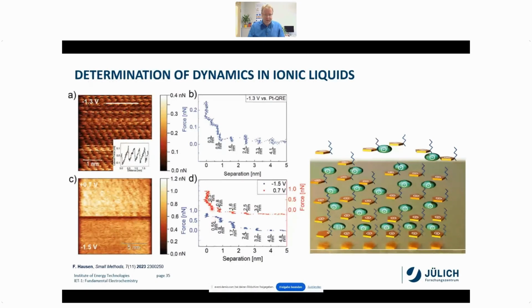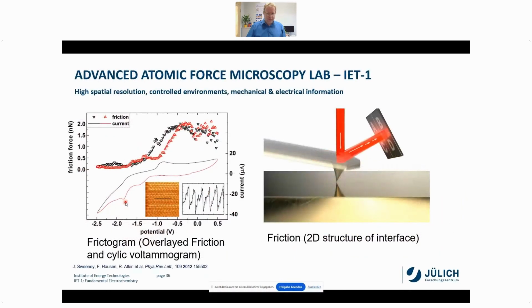And now you might wonder, if we have a positive potential, why this is the cation. That is just because we're scanning here not at the substrate, but we're scanning at these anion layer. So the first layer which you penetrate through is the cation, and at negative potentials, vice versa. So we can see here that we are not at the gold film. So if we now look at these layers and put them on top of each other, or what you can see here is basically, if we record a cyclic voltammogram again in this ionic liquid, that we basically have at each of these signs where we see something in the electrochemical signal also changes in the friction. So showing again that friction is really sensitive to changes at the surface.